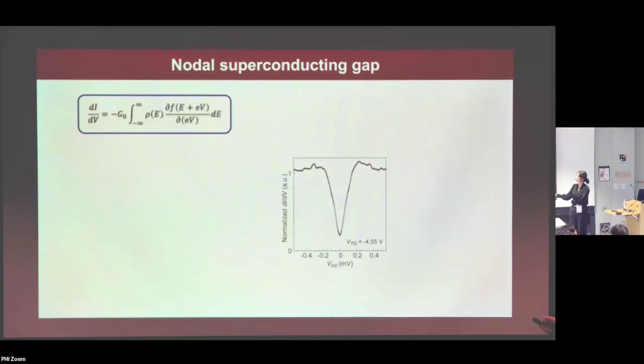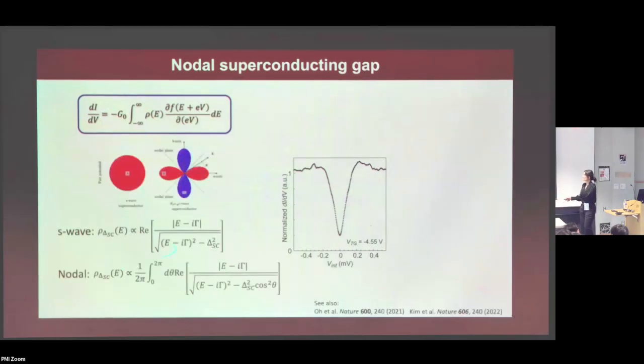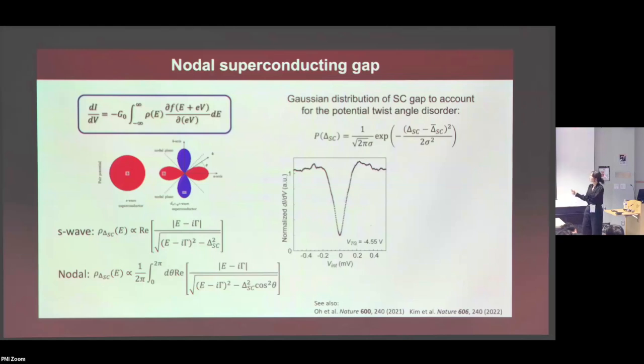Okay. So when we do that, the curve looks like this, and we want to study this curve. The tunneling conductance is proportional to the density of states, and there's some standard Dynes formula that you can use for both the S-wave gapped phase and also nodal pairing, for both P and D waves. But in addition to these fits, we incorporated another factor, which is the distribution of the superconducting gap, because we know for a fact that we're not doing atomic scale tunneling. We have this finite size tunnel junction, so it's likely that there might be some superconducting gap, twist angle disorder, maybe the TC and gap size are different. So we also take into account this sigma for that.